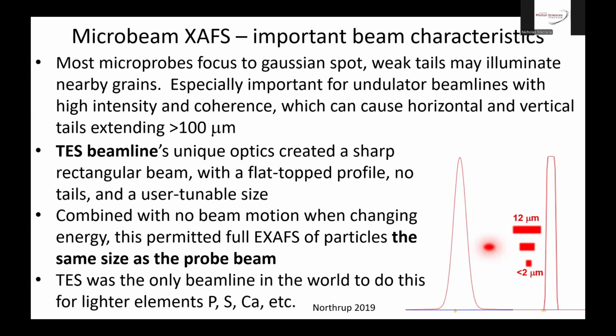So it's also important to understand more about the characteristics of the beam that you're using for microbeam spectroscopy. As I said, most microprobes focus on imaging, so they focus to a Gaussian spot, kind of like in this left example here. It's a nice hot spot, but it does have fuzzy tails. And even though these are small tails, they extend quite a ways out from the central spot, and even though they're weaker, you might be trying to measure something that's a low concentration of an element, but nearby is something that's a weight percent concentration of that element.